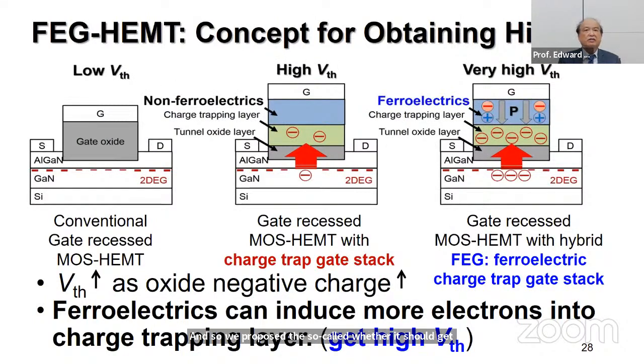In this way, the first one is conventional gate recess, on the left, where the threshold voltage is not high enough. And then you can put some non-ferroelectric material with negative charge on it, but then the charge is not high enough to get a high VTH. The best way is the one we propose: use ferroelectric material along with the charge trapping layers beneath it.